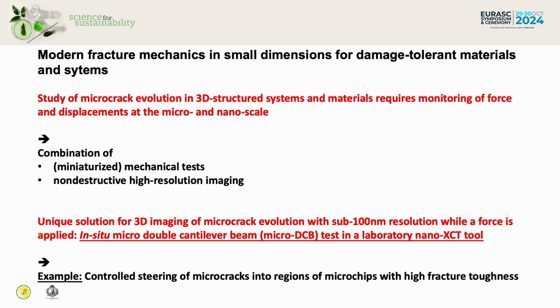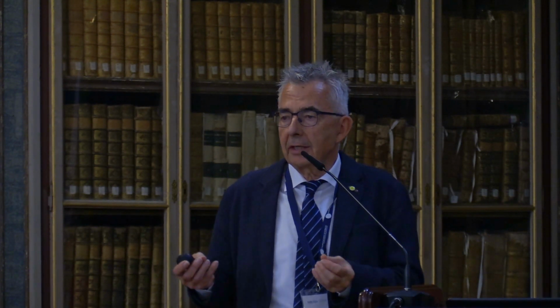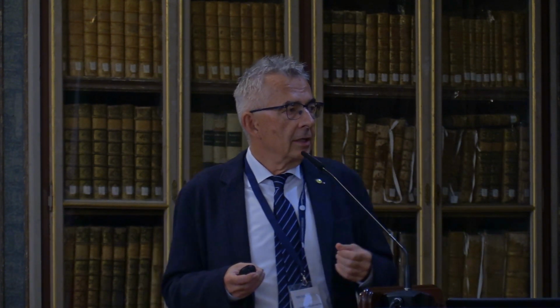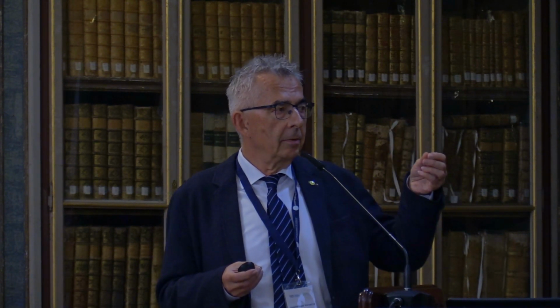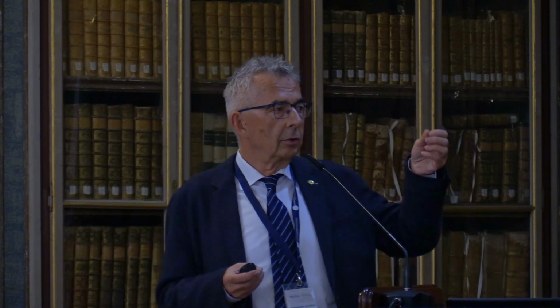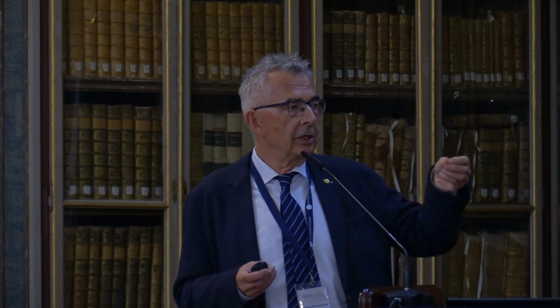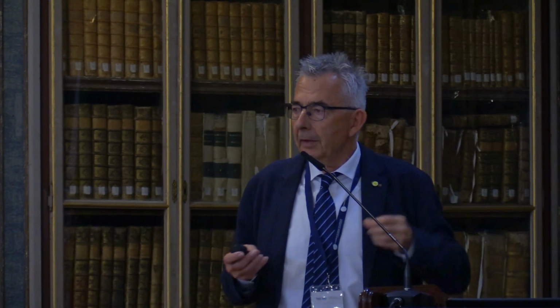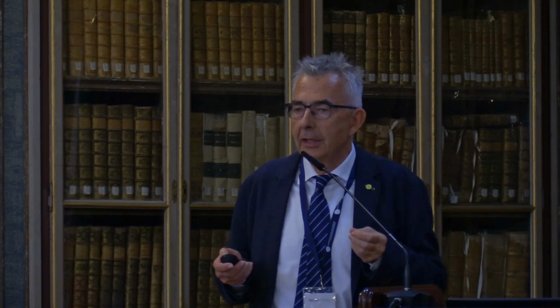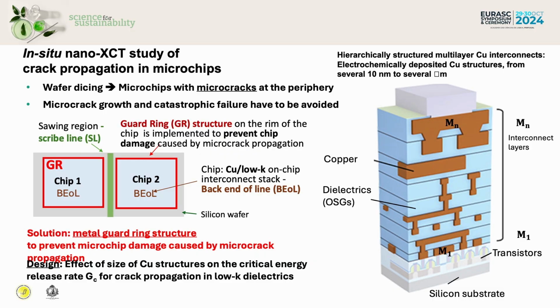So that means modern fracture mechanics in small dimensions is a completely new field where, from the experimental point of view, we need a miniaturized mechanical test, and we need non-destructive high-resolution imaging. And if we want to do experiments in situ, then this experimental technique has to be non-destructive. And I will show that it is possible to have a controlled steering of microcracks into regions with high fracture toughness, also for engineered systems, for instance, for microchips.